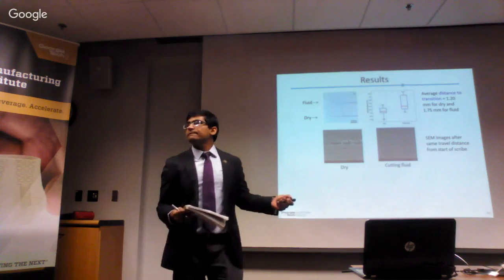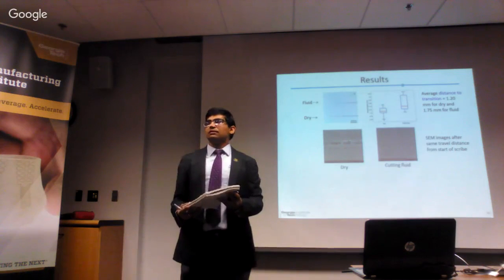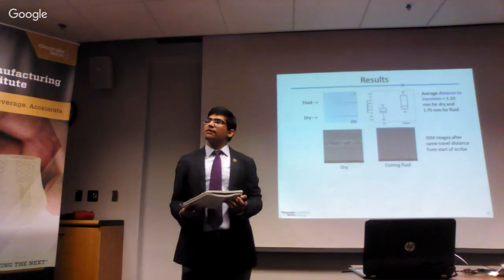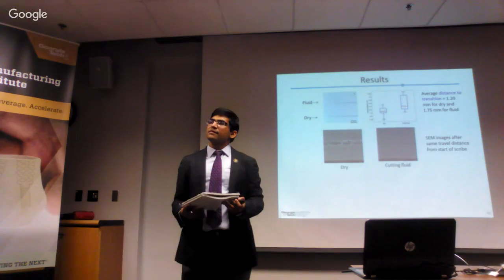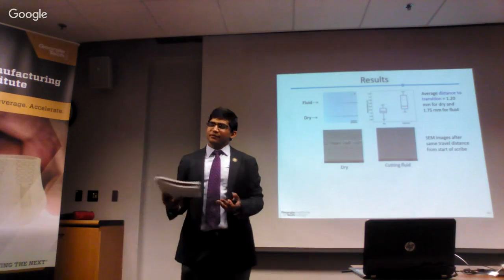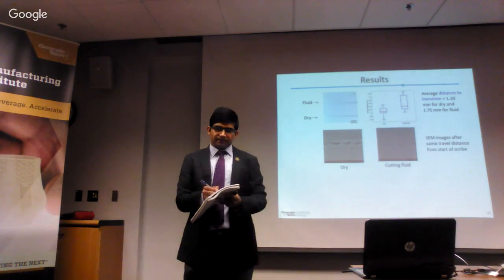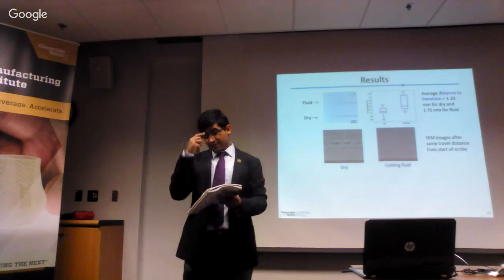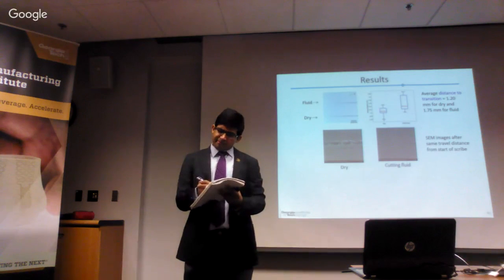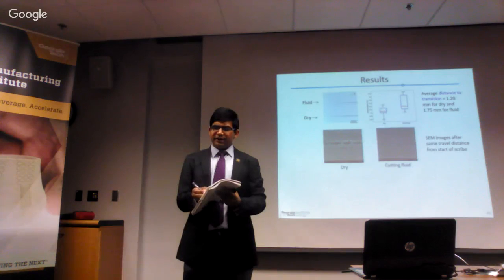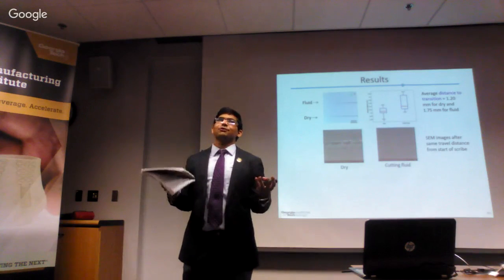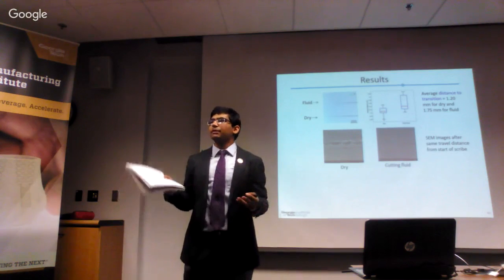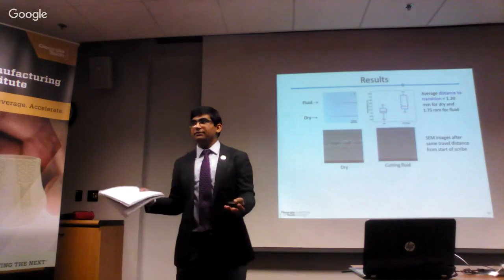Yeah, but the question really is the depth. If you were indenting, forget about the scribe, if you're just indenting with and without fluid, and if indeed the fluid is bearing some of the load, then I would expect the depth of that indent to be different, even if you're applying the same load. So did you notice any difference in the actual indentation itself? The indenter here is programmed to indent at a constant load. We don't compare the depth, but what you're saying is comparing the indent depth. Yes, and that is fine.